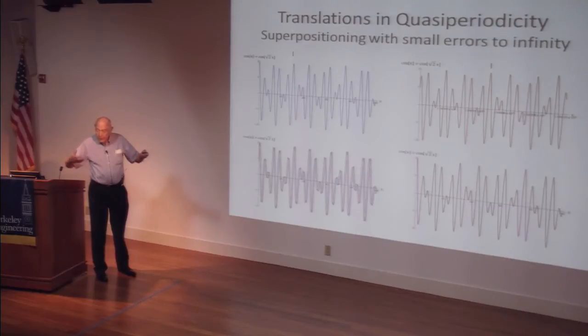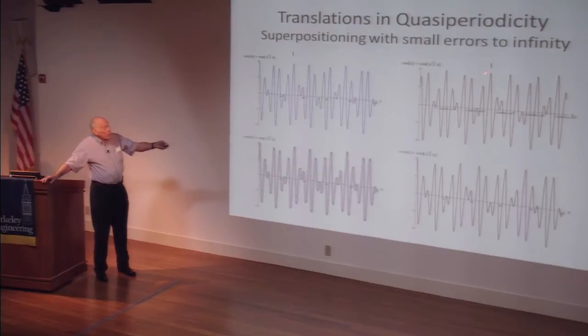So with quasi-periodicity, things repeat. But the translation from this to 1,000,000 that produces this, if I try to go to 2,000,000 and find this peak, it won't be quite as high. And if I go to 3,000,000, so the translations are not a periodic set. They are peculiar, and what they are is a line on an xy plane that starts from the origin and goes up with a slope of the square root of 2. Every once in a while it gets very close to a lattice point, and that's a translation. But it's a certain distance away from that translation. Twice as far would be twice as far away, so it won't be as good a fit. But they'll come in aperiodic ways.